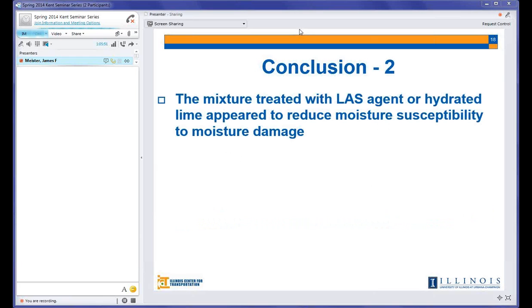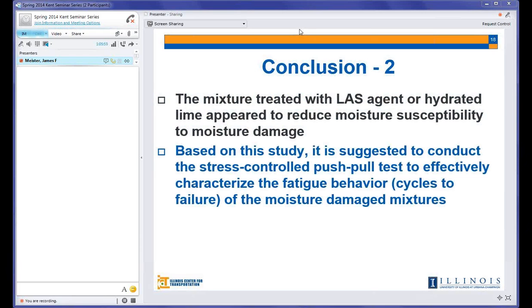We saw that liquid anti-strip and lime in both tests have resulted in reducing the moisture susceptibility of the asphalt mixes. And based on the results of this study, we found that it's better to run the push-pull test if we want to see better prediction of fatigue in the field under stress controlled rather than strain controlled.